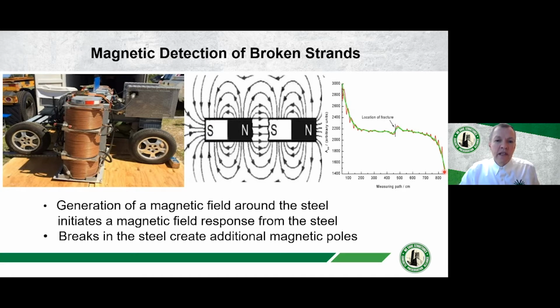If the tendon is completely severed, then you'll end up having two curves. You'll have south going all the way down to north, and then you'll start with a new south up here, and you'll come down all the way to south if it's completely broken, as illustrated in the little bar magnet in the middle here. More likely what you will see is that only a portion of the steel is broken, and that's going to give you a kind of result that you see here, where you have the majority of the steel going straight through, but where you've got the broken strands or the broken wires, it will tend to create a new north and south pole at the location where you have the defect.